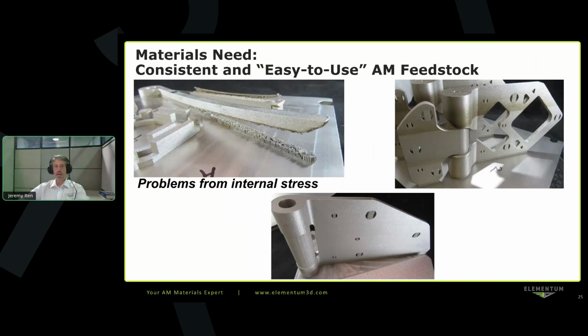So what we really need for additive manufacturing, we need consistent and easy to use AM feedstocks with high performance. Here's some examples. In this case, printing 17-4 precipitation hardened stainless steel. And you can see the problems with internal stress causing those parts to delaminate from the plate. The internal stress causes the parts to kind of smile right off the plate and come loose, curve. You can get part distortions. You're not producing the geometries you want to produce. You're losing contact with the plate, which can lead to complete build failures. And so this is a big problem.